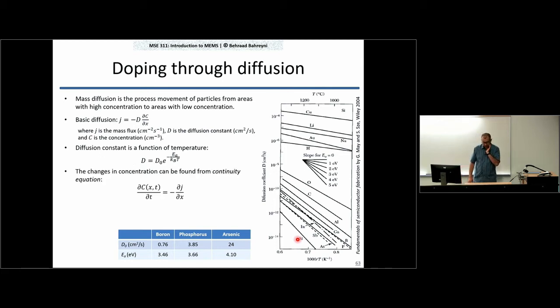Now, we also look at the continuity equation. It says that the change in concentration of a material at a location is going to depend on the flux of the material that you take away from it, and the changes in that flux relative to location. And combining the continuity equation and your basic diffusion equations, you get Fick's law, which says the changes in C with time are proportional to the second derivative of C. C is the concentration with length. It's a 1D problem we are considering right now, okay? And the diffusion constant determines how fast that happens.